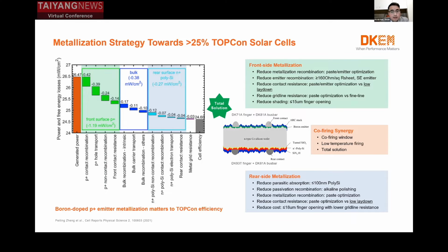With this kind of request, we have to achieve very good contact resistance, either to enable lower laydown or to enable better EL yield. That's very important. The last one for the rear side is that we still need to enable fine line printing, here less than 18 micron finger opening. The third category is the co-firing process.